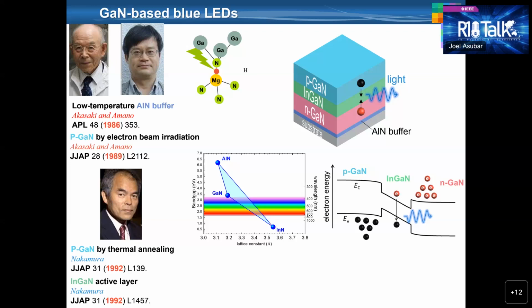When forward biased, electrons from the N-GaN and holes from the P-GaN are injected into the InGaN active layer where they recombine. And the energy lost by electrons during the recombination process is converted to photons, whose energy is approximately equal to the band gap of InGaN, corresponding to blue light.